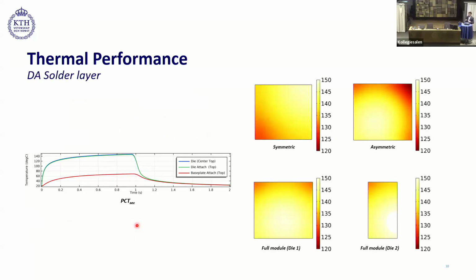Looking at the temperature distribution in the die-attached solder layer. Here we are looking at during PCT-SEC. We see that depending on the location of the die inside the package, the temperature distribution also varies. For example, in symmetric condition, the high temperature region is presented towards the central region. This represents the center part. However, in asymmetric, the high temperature region moves more towards the corner.